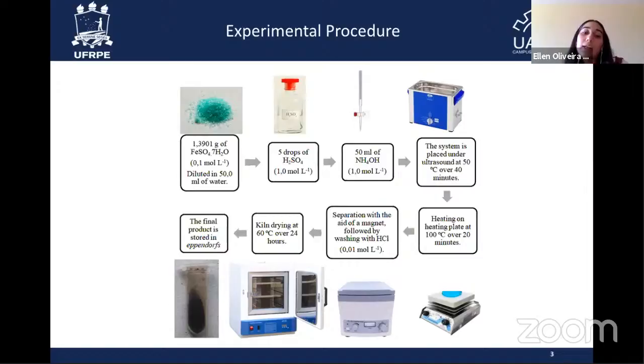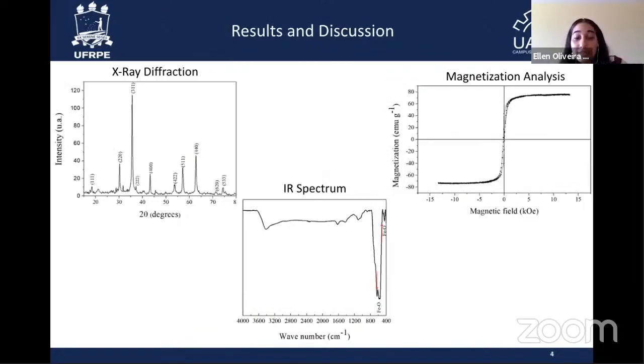And with the aid of a magnet, we decanted the nanoparticles, washed them with hydrochloric acid, and then we placed them in centrifugation and drying for 24 hours at 60 degrees. After the synthesis and the drying period, we obtained a fine and magnetic powder. We proceeded with the characterizations of X-ray diffraction, infrared spectrum, and magnetization. As we can see, the tetragonal phase of maghemite was indexed, and with the hysteresis curve, we observed that the particles have ferromagnetic behavior.